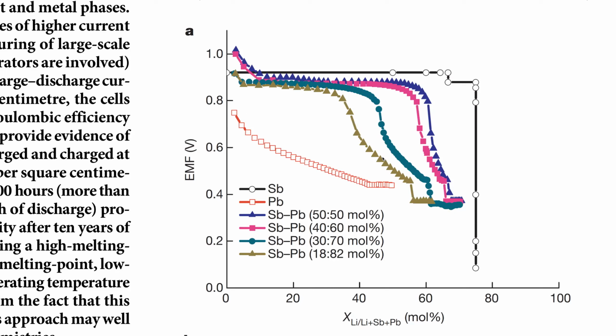And I said, well, let's see what it's like. Maybe you get a substantial decrease in operating temperature with a modest decrease in voltage. This was the surprise. The voltage stayed high. The voltage stayed high because when the lithium went into the antimony lead, it reacted preferentially with the antimony. And so we got the low melting eutectic temperature for operating, and yet the high voltage of antimony. And that was the discovery that warranted the Nature paper.